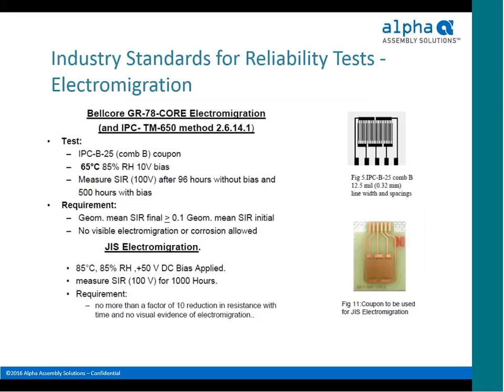Electromigration is very similar. What you have with electromigration is the same kind of conditioning with different environmental conditions applied. So it's a slightly different coupon. It has tighter spacing than the IPC-B-25 and the Bellcore test method, which mimics the IPC test method. But the test condition is 65 degrees C, so higher temperature, 10-volt bias, and you measure the SIR after 96 hours without bias and after 500 hours with, looking for, again, a relative comparison of the before and after resistance to get your pass-fail criteria, in addition to visible test requirements for no visible corrosion allowed.